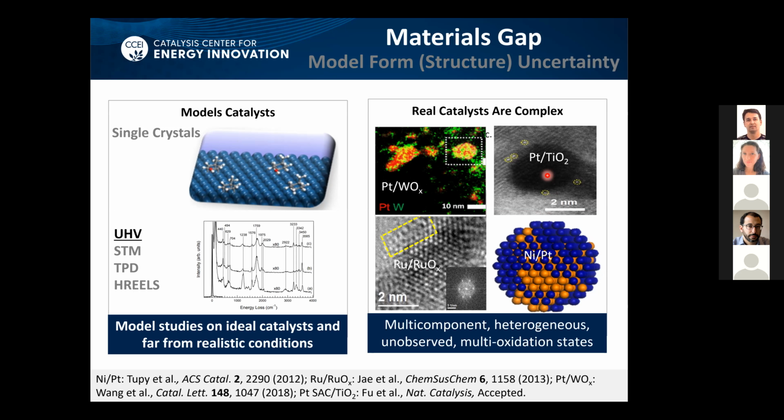This image on the top right is a fascinating one. You can see single atoms of platinum with aberration-corrected microscopy on a titanium dioxide nanoparticle. These single atoms or even dimers are impossible to see with a regular high-resolution microscope. It's only with the new techniques that you can actually see them. And in many cases, these atoms are believed to be the most active ones, doing the catalysis of the nanoparticles. So it is really the things we don't see that do the catalysis.